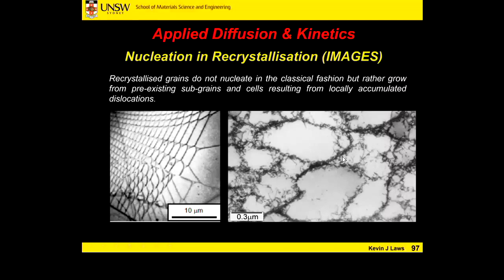Here's an example in metals. All these squiggly little lines that look like a bit of cotton wool or hair on the microscope lens, again, this is under a TEM. We can really only see dislocations in a TEM, not an SEM. We can see they start to get tangled up with each other and form these subcells.